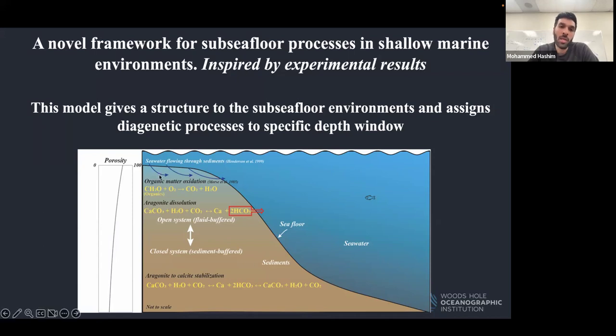One is that if in the open system you cannot form calcite, then you are probably just dissolving aragonite. And if there is advection of seawater, that alkalinity that is released from the solution can be released to the open ocean. So that can be a flux of alkalinity from the subsea floor environments. The other point that we made was that aragonite to calcite stabilization only happens with burial in a closed system, which has implications for the geochemistry that is recorded in the calcite that gets buried.